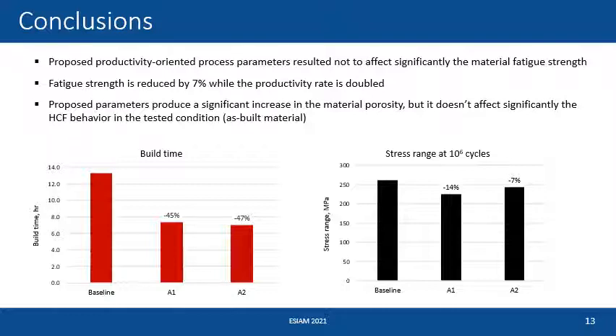We saw that the productivity-oriented process parameters produce a significant increase in material porosity, increasing the porosity and reducing the material density, but also increasing the dimension of the single pore. But in the tested conditions, we saw an almost null effect on the high cycle fatigue behavior of our specimens. Future developments will deal with a better investigation of the surface roughness, its characterization, and also further investigation on fractographic analysis of our specimens.